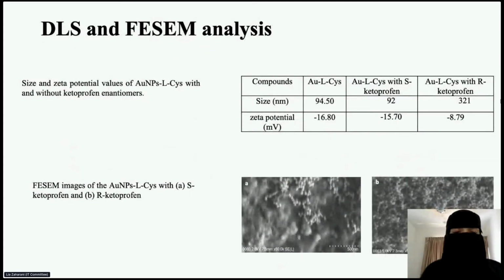So dynamic light scattering and FESEM analysis were done to see the size and the stability of the gold nanoparticle before and after introducing the Ketoprofen enantiomer. The size here is 94.50. After I introduce S-Ketoprofen, it's similar, 92. And after I introduce R-Ketoprofen, it increased to 321. That shows the massive aggregation of gold nanoparticle.